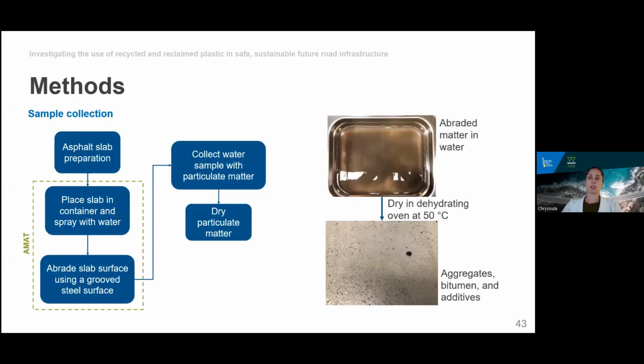Now, to understand the potential release of microplastics by the manufactured and aged asphalt slabs, we use the custom-developed abrasion device to abrade the surface for 1 hour. The slabs were sprayed with water to prevent overheating due to friction and also capture the released dust.